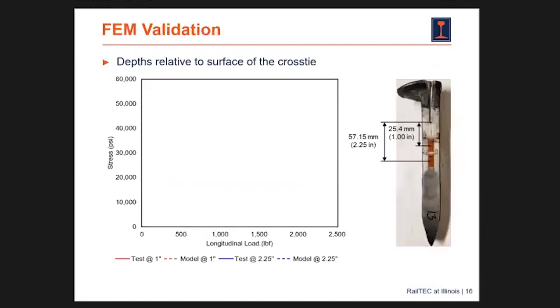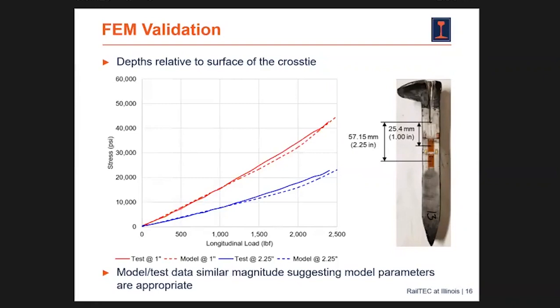And the first thing we wanted to do is create it and validate it. And again, Shushu did a wonderful job working with us. We again used one of our instrumented spikes, and she was able to look at the test would be our laboratory value coming from our instrumented spikes, and the model is what she is outputting with her developed model. And at both 1 inch and 2¼ inches into the tie, she gets very good agreement with her model. And so we considered this to be a validated model, something that we could use going forward to do a sensitivity analysis or a parametric study of changing the materials.